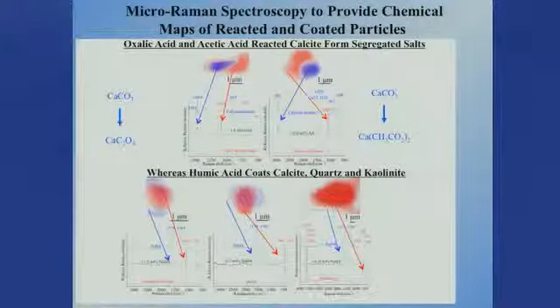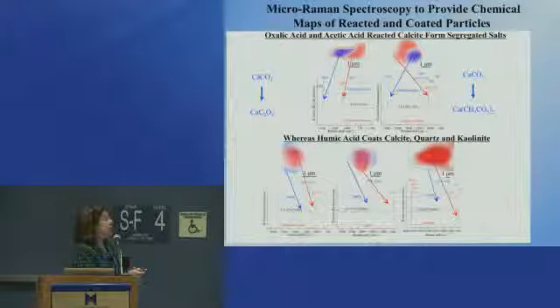And what we're able to see is that we end up getting phase segregation. So now these are Raman spectra of calcium carbonate versus calcium oxalate, and then here's the reacted sample in the middle. Here is calcium carbonate, calcium acetate, and the reacted sample in the middle. So we get the spectrum, we can see bits of each of these, and so this undergoes chemistry, but the point I want to make here is we see this phase segregation between these two different reacted species.